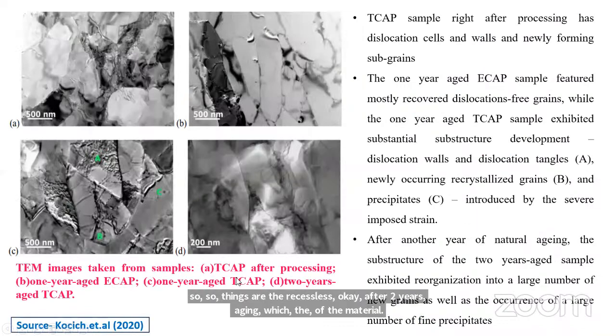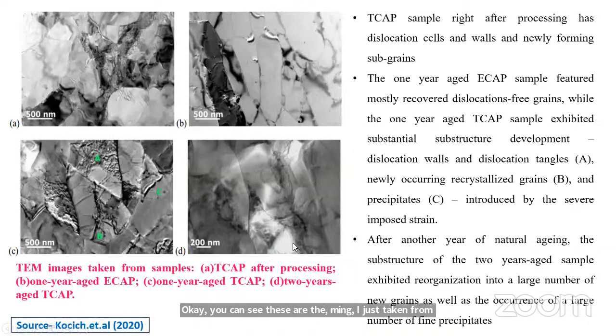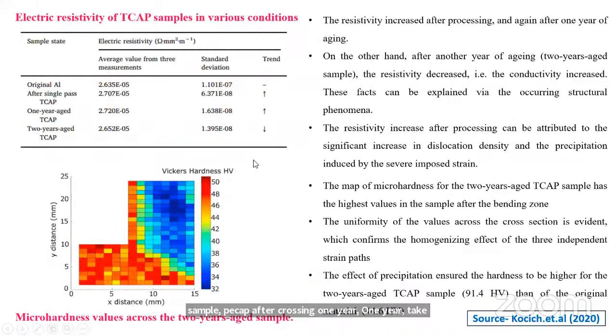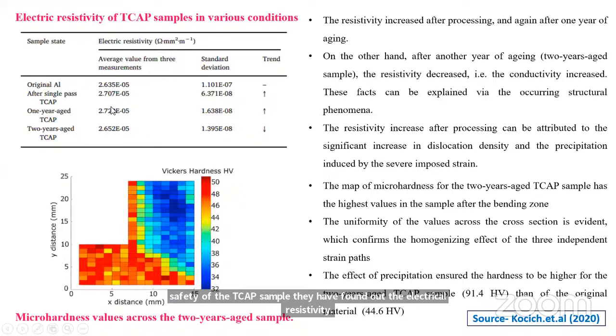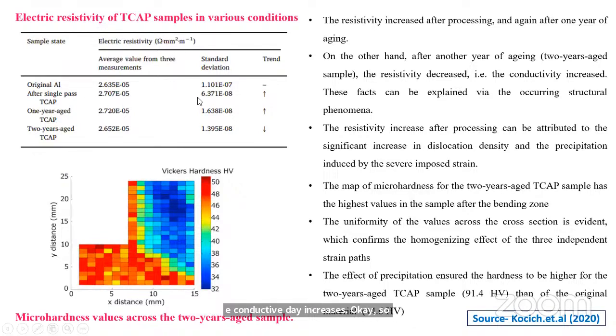You can see these are the images taken from the TCAP sample after processing, 1 year aged TCAP and 2 year aged TCAP. Right. So they found out the electrical resistivity of the TCAP sample. As the electrical resistivity decreases, the conductivity increases. After single pass, the electrical resistivity is 2.707, after 1 year 2.720, and the 2 year aged sample has an electrical resistivity of 2.65 × 10^-5. This indicates that as the electrical resistivity decreases, the conductivity of the sample increases. So this is the inference from this.